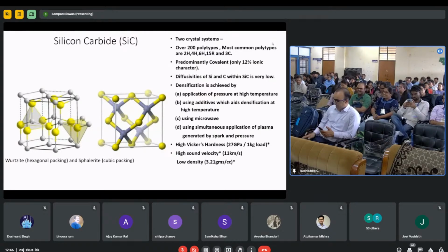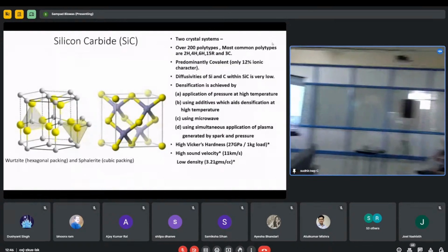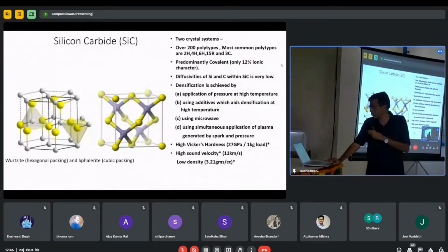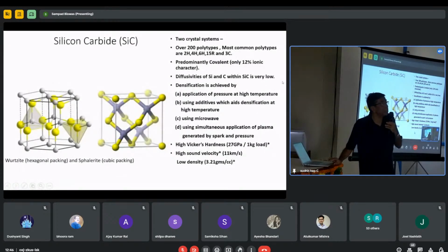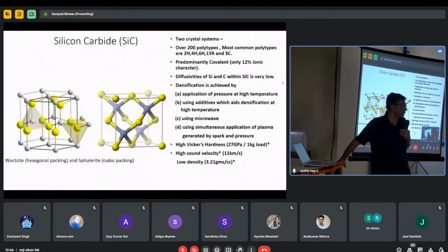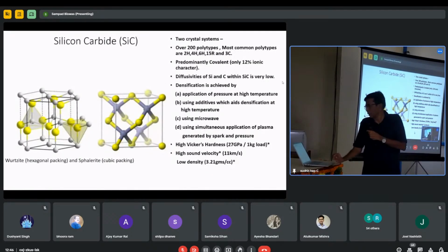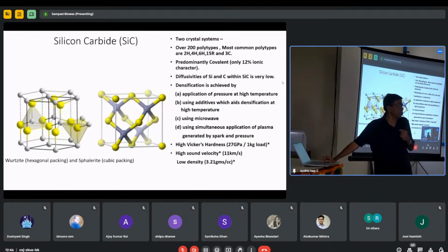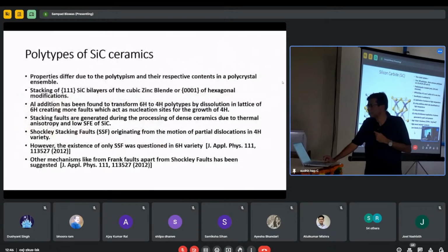So it has got a very high Vickers hardness, about 27 GPa, at 1 kg load. And it has got a high sound velocity. That is most important. This high longitudinal velocity as well as transverse velocity within the ceramics. Solids have got much higher sound velocity. That is very important for armor applications. And as well as it has got a low density, about 3.21 grams per cc.